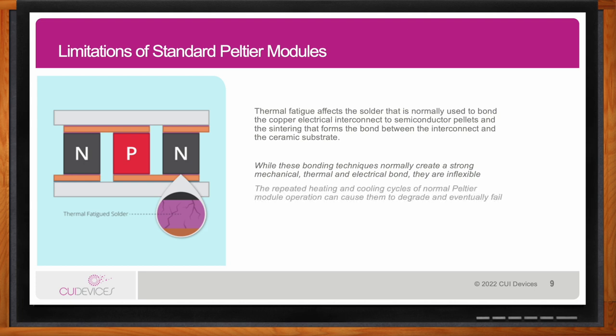In particular, thermal fatigue affects the solder that is normally used to bond the copper to the semiconductor pellets and the sintering that forms the bond between the copper and ceramic. This is also known as thermal expansion contraction, or slight variations in the physical size of the pieces of the Peltier module. What this does is it causes small cracks and has a negative effect on the performance of the Peltier over time. As I said earlier, they're solid state devices, so we're talking a rather long time in general here, but this thermal fatigue is the major limitation and failure point when it comes to Peltier modules.